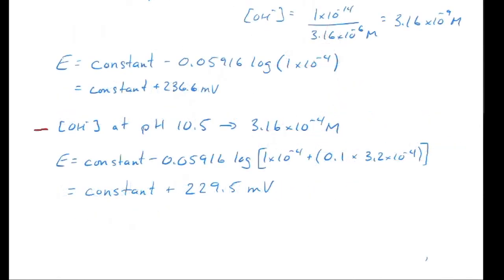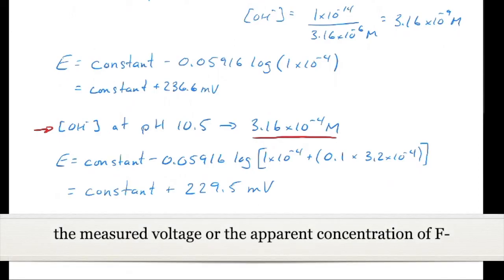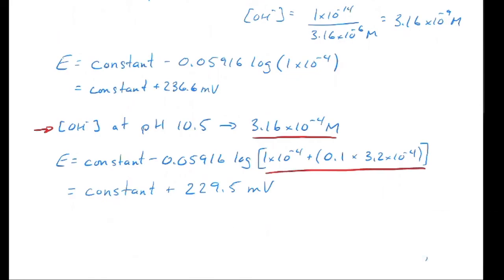So now let's figure out the concentration of OH minus at pH 10.5. We use the same process we did at pH 5.5, and we get 3.16 times 10 to the minus 4 molar. So that's quite a bit higher than it was at pH 5.5, which makes sense. pH 10.5 is much more basic. So now, even when we multiply this number by 0.1, it's going to be on par with the concentration of fluoride, right? The concentration of fluoride is 1 times 10 to the minus 4. Multiplying the concentration of OH minus by 0.1 makes it on the order of 10 to the minus 5. So adding the concentration of OH minus, even with the selectivity coefficient, is going to change the concentration of fluoride. So we're going to have to include that in our equation for selectivity.